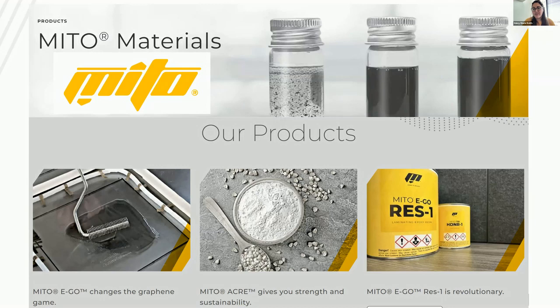And we saw this as a unique opportunity to see if we were able to coat graphene onto the carbon fiber through the sizing agent. So we developed what we are now calling Ligra, which is liquefied graphene. It's a water-based solution. And we were able to introduce that into the sizing process at Vartega to coat the recycled carbon fiber bundles, and then put that into a plastic part.